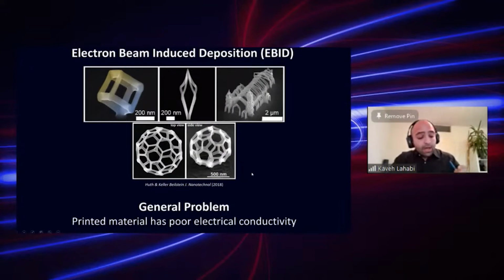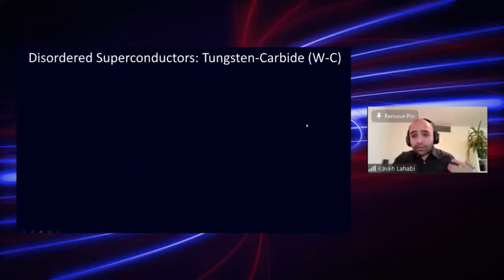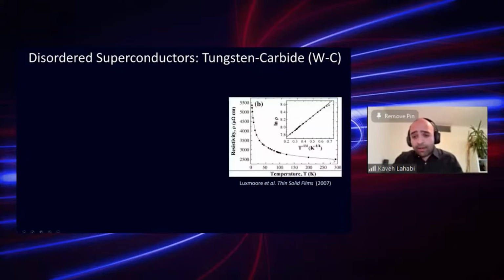But if something is not a good conductor, it can be a very good superconductor. And tungsten carbide is an example of this. So there were a lot of efforts to make superconducting tungsten carbide using this technique. Unfortunately, however, most of these studies found no sign of superconductivity. And what you see here is that as they go down in temperature, the resistance just shoots up, and there's no superconducting transition.